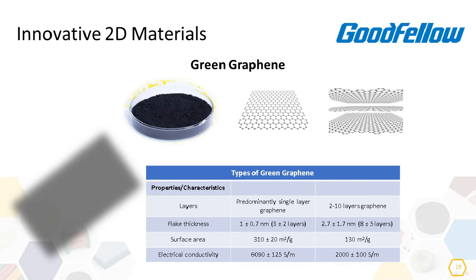Goodfellow here is presenting the only high purity green graphene produced by a highly scalable, chemical-free process. This process involves breaking methane, a potent greenhouse gas, as we know, which is a harmful byproduct of processes like farming, landfill, or palm oil milling, into elemental hydrogen and carbon in a plasma reactor. The graphene is formed, and the elapsed time of this process is less than 1 second, and that's very important because we can understand the high scalability and the quantity that we can make during this process.